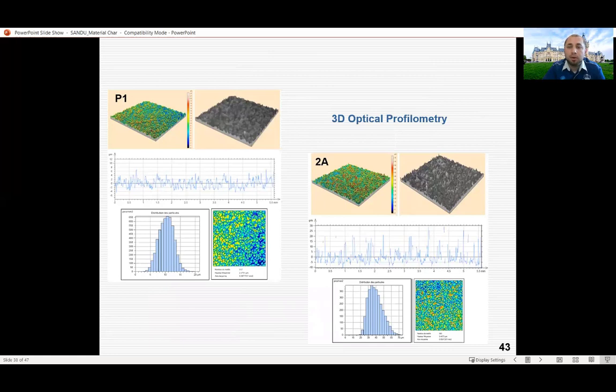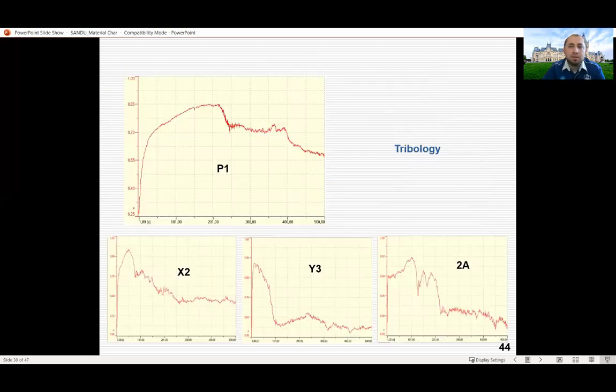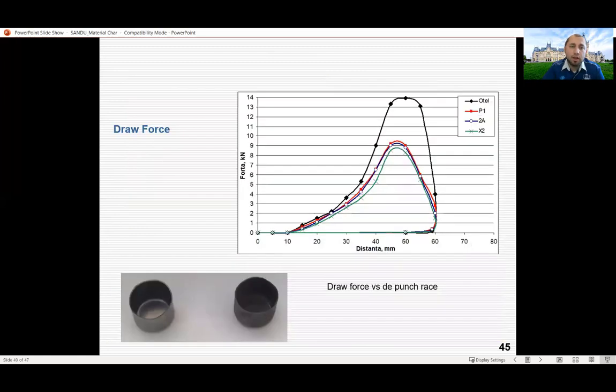And then we have the optical profilometry, similar to the atomic force microscopy, where we can get the topography, the micro topography of the layer obtained by us. We can identify the granulometry and the surface area, many interesting analyses. We are short in time. We have the tribology, where we could measure the time until our layer was destroyed. You can see here the drawing force to get better results. As you can see, the black means the steel sheet, the regular steel sheet. And after we deposited the lubricant layer, you can see the force required to deform these samples dropped by half. So that means a prolonged time of usage for the devices that we're using in there.